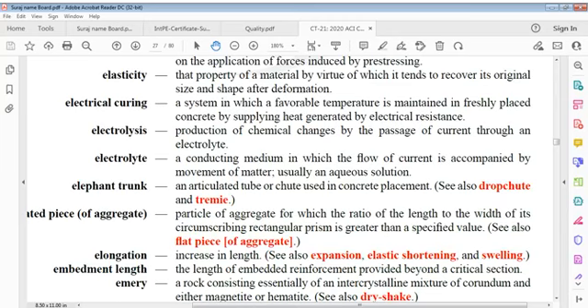One researcher applied DC current to cement paste which had different water cement ratios 0.4, 0.45, 0.5, 0.55, and different mineral admixtures, fly ash, silica fume, and blast furnace slag, at different ratios by weight 0%, 10%, 20%, 30%. The result of their study is that applying electrical current can be used for obtaining rapid setting time on cement paste with high volume mineral admixture. Also, Gundo found that the duration of final setting time was shortened as the amount of cement and concrete and voltage level increased.